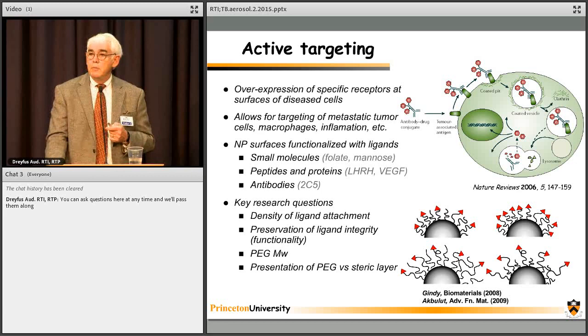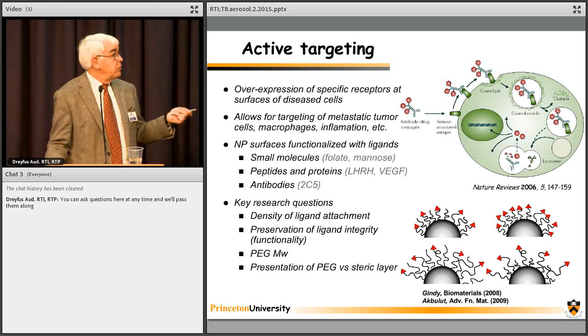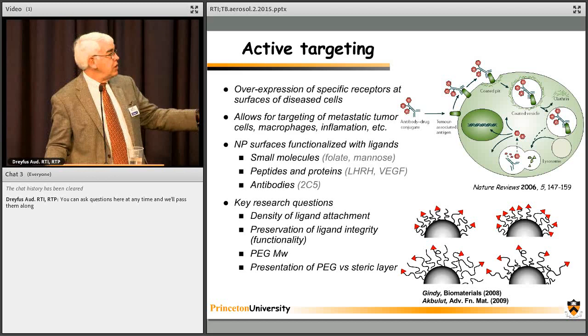These two figures have exactly the same number of ligands on that surface. That just happens to be shorter chains, and those are bigger chains. What's better? Okay, same density number on the nanoparticle. Well, you'd say maybe the bigger chain's better because it can reach out further on the surface and find more receptors more easily. So maybe that's better. However, the larger I make the polymer chain, the more dilute I make it in end groups, because the main part of the chain occupies a big volume, and there's only one end. So is it better to use a big chain that can reach out, or a smaller chain where the ends are actually more concentrated on the surface?